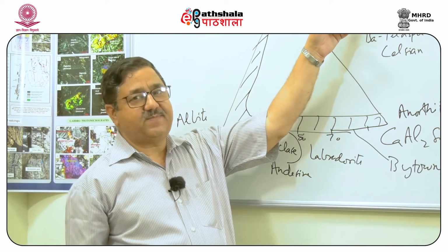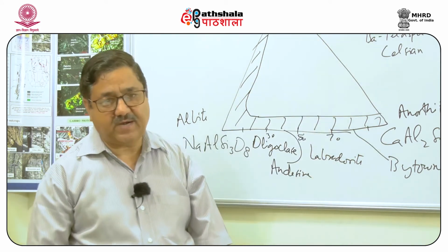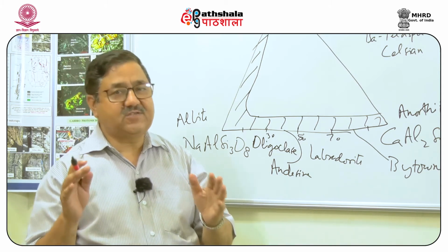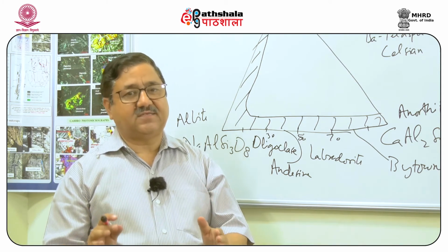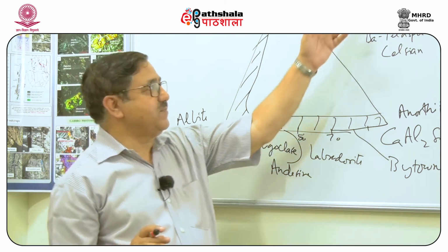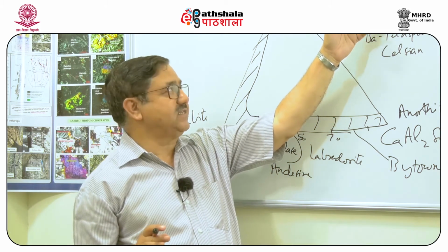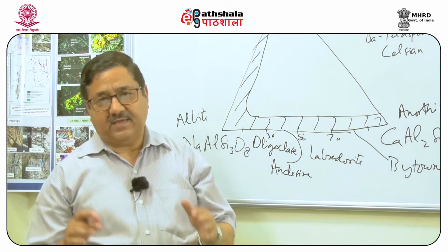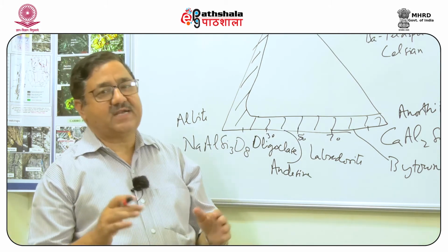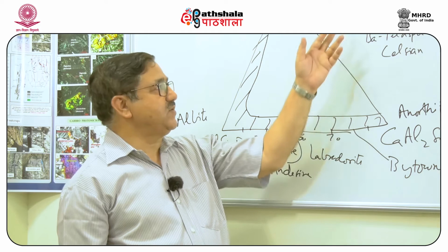Amongst the potassium feldspars, the sanidine and the orthoclase represent a disordered tetrahedral site, which means that they are monoclinic, and I will explain the structure just now, and the collapsed structure, or a triclinic or lower symmetry structure, is known as microcline.